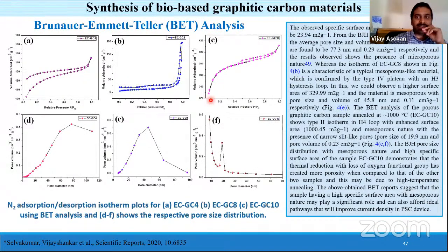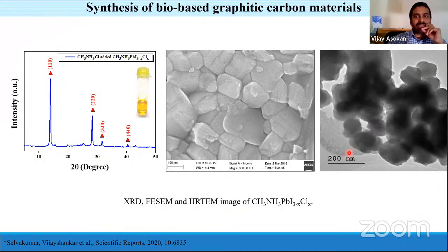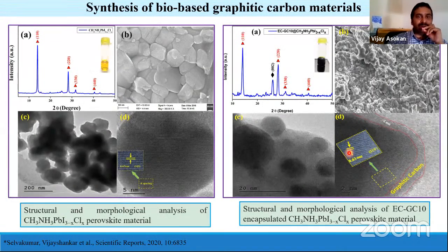We also used BET analysis and calculated the different pore parameters and surface area parameters. If you see, with the 1000 degree annealing temperature, the surface area is enhanced to 1000 square meters per gram, with the pore size reduced to narrow slit-like pores of 19.9 nanometers. That's the success of this annealing temperature. So this is the basic perovskite material we synthesized. We used this perovskite material and combined it with the HTM material, which we make using graphitic carbon materials. Here from the TEM image, you can see how the graphitic carbon is layered around such perovskites. We have not only used a carbon-based HTM, we also used an interface layer using perovskite and graphitic carbon material. That's why we combined these.